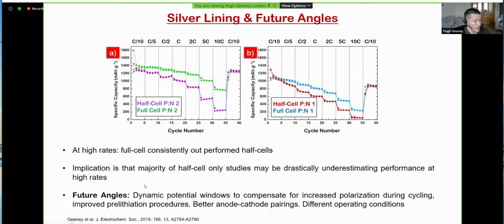The future angles on this work would be to look at dynamic potential windows. If we have increased polarization during cycling, where our processes are moving out of our voltage windows, we may need to increase the upper cutoff while also avoiding lithium plating. And the big one then is improved pre-lithiation procedures. Also looking at better anode cathode pairings. Again, there is scope for potentially increasing this high rate performance by looking at a cathode material that is particularly good at high rates, and also different operating conditions. Work is already underway where we're looking at these full cells at both high and low temperature, in terms of trying to improve the performance.